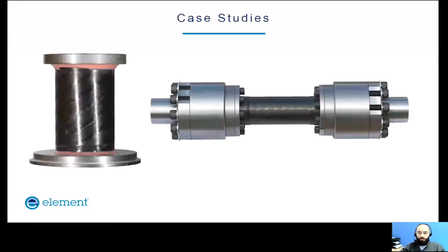So, examples of the compression and tension samples used in the test can be seen here. It is recommended to move away from bonded joints in tension testing and use a mechanical gripping system to ensure that the bond line is not tested. The last thing that you want is to run a lifelong test and 10,000 hours down the line, your bonded joint fails and your test has to be suspended because you haven't tested the material itself. So on the right hand side, the picture shows a mechanical gripping alternative to the bonded joints used in the ASTM D5450.